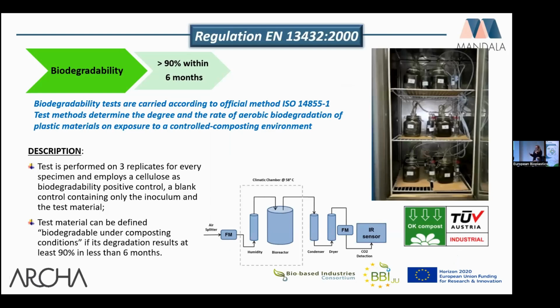For the biodegradability, I don't know if all of you know this test. We performed the test according to the ISO 14855, and we quantified the CO2 that is produced by the polymer used in the formulation, in aerobic conditions, by determination of this CO2 and quantification of the percentage of biodegradability compared with the organic carbon that is in the polymer. The requirement is that biodegradability has to be more than 90% within 6 months. All this testing was performed according to the OK compost industrial scheme that is provided by TÜV Austria.